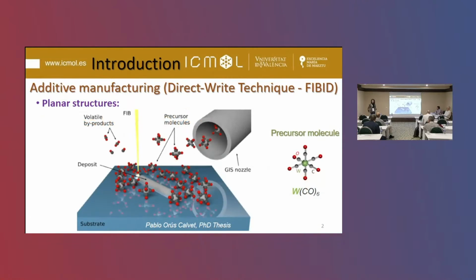This is a general sketch of the additive manufacturing technique, called focused ion beam induced deposition. The precursor molecule that I use for the fabrication of nanosuperconductors is tungsten hexacarbonyl. Those molecules are delivered from this nozzle and absorbed at the surface of a substrate, and the focused ion beam is scanned over the surface, partially decomposing those precursor molecules, forming a deposit.